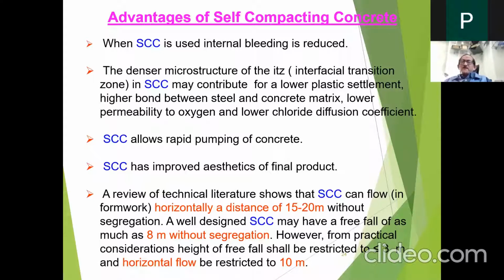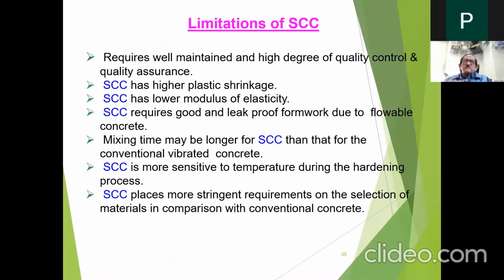The review of technical literature shows that SCC can flow horizontally a distance of 15 to 20 meters without segregation. A well-designed SCC may have free fall of as much as 8 meters. However, from practical considerations, these distances are restricted to 10-meter horizontal flow and vertically less than 3 meters. So that segregation is further reduced, or we are not inducing any segregation due to mechanical efforts.